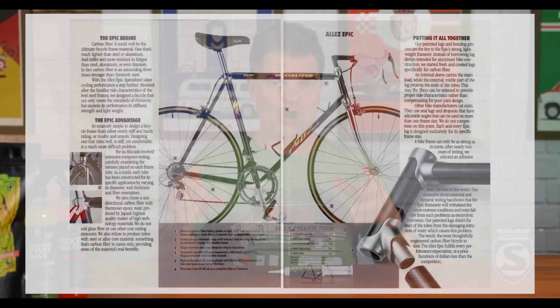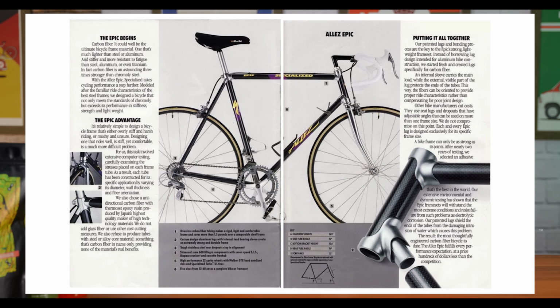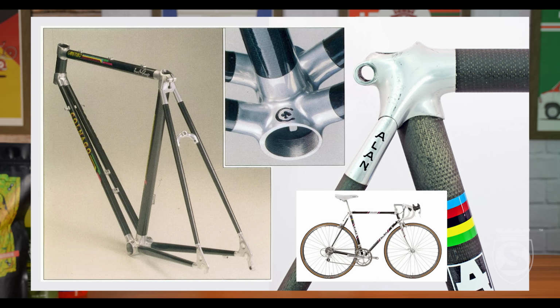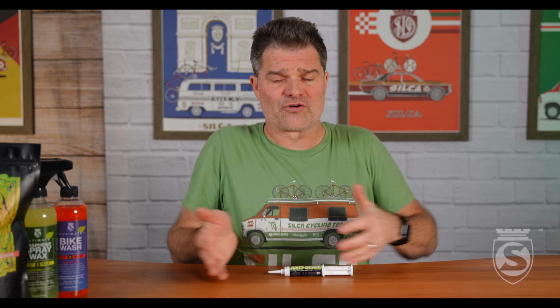We've got aluminum. And for those of you who were around in the late 80s, early 90s, carbon fiber with aluminum lugged frames from Specialized Allez was a well-known one, but Vitus and Alan and TVT, they were bonding carbon tubes to aluminum lugs, and within 4, 5, 6 years, pretty much 100% of them fell apart. And they didn't fall apart because they were under-engineered or because they were overstressed. They fell apart because you get a little bit of sweat and a little bit of water in the interface of that bond line, and you start swapping electrons.